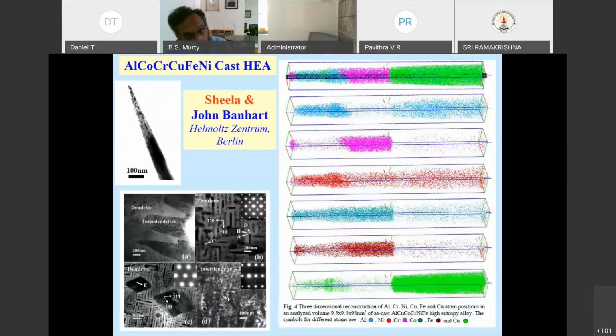At the same time, for such multi-component alloys, depending on the technique by which you prepare them, it is possible that you can have heterogeneities inside the sample. Here you have more or less a 2-phase microstructure. One phase is rich in one particular type of element, another phase is rich in another type of element, and this kind of thing can also be found out very easily using atom probe.